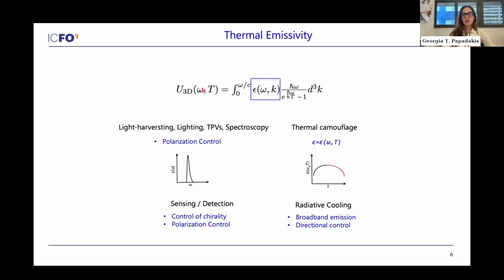So this equation here shows you that the energy density of emitted photons out of a hot body is simply the integration over all wave numbers of the thermal emissivity of the material times the energy of the photon, h bar omega, times the photon occupation number, which is this fraction here. So now if I integrate over all available wave numbers from 0 to omega over c, I will get the photon energy density.